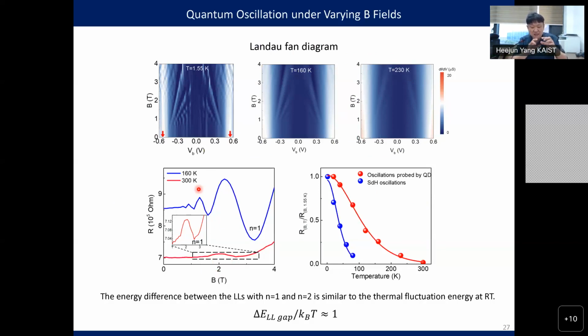So somehow we select a certain area of the graphene channel. This is tunneling between two graphene layers. We have a large area, several micrometers by several micrometers, but we have a certain defect location with a certain period. And then we can select a certain area of the graphene channel, which has uniform Landau level, no Landau level broadening. So we can measure the Landau level difference at room temperature at 2 Tesla. I like this result because we could measure it at room temperature.